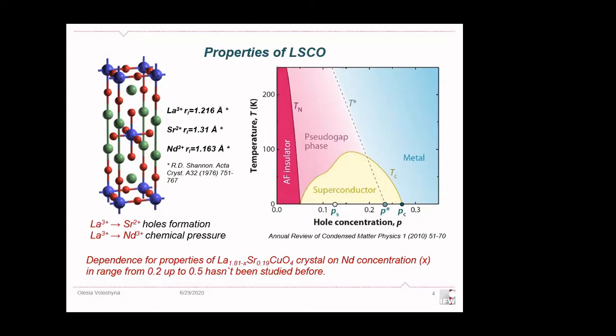And if we take a look at the phase diagram for the LSCO, we can see that with increasing hole concentration in the compound, the LSCO goes from the antiferromagnetic insulator to the metal. And somewhere in between, at an optimal doping of the holes, we have the region of the superconductor. And above the superconductor region, we have the so-called pseudogap phase.